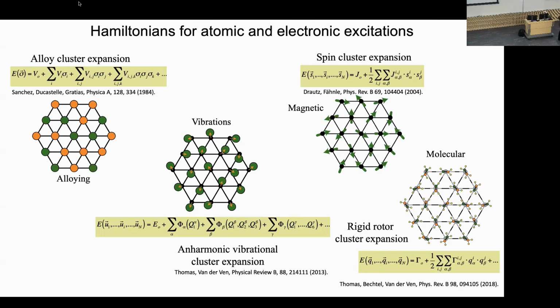And if you have molecular crystals, you can do it in terms of molecular orientations. You can do something like this, where you have a similar kind of expansion, but now in terms, let's say, of quaternions, which is a way to keep track of the orientations of molecules. So these are all very useful and mathematically rigorous tools with which we can express the dependence of the energy of a crystal on different degrees of freedom. And in fact, this cluster expansion method, which was triggered by this original paper in 1984, is a very rigorous mathematical formalism to formulate and express these cluster expansion Hamiltonians.